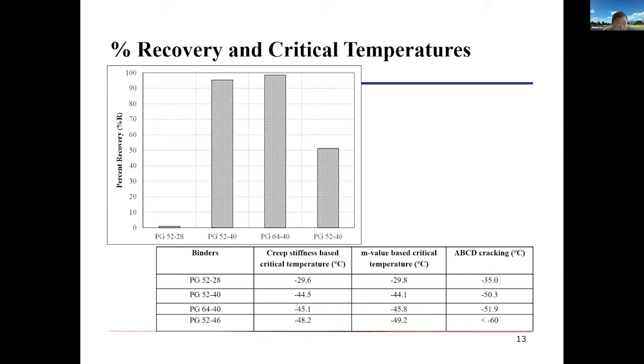And here are results of percent recovery values at 3.2 kPa for the studied asphalt binders, and also the critical cracking temperatures from a low temperature performance evaluation. As we can see from this figure, the unmodified binder showed nearly no recovery, less than 1% recovery, but the others had a very high percentage recovery, which implied they are more elastic at high temperatures.